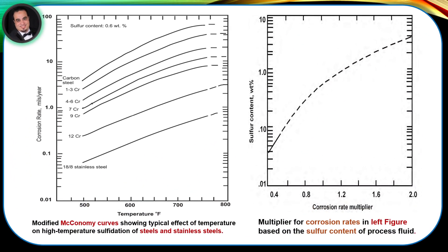Figures show the typical effects of increasing chromium content, temperature, and sulfur content on metal loss. These curves only indicate the general trends in the effects of chemical composition, temperature, and sulfur content on corrosion rates. They are used in design for estimating the corrosion rate for a particular service but should be regarded as only showing trends, as actual observed rates can often vary substantially. In many cases the predictions are conservative — for example, they overstate the actual corrosion rates found in service.